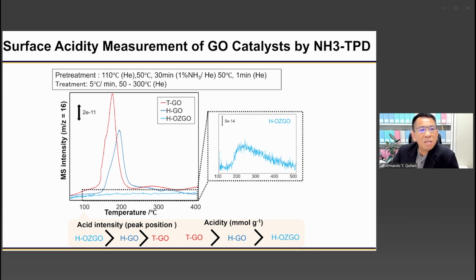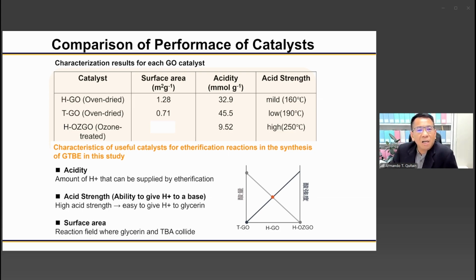We tried to analyze the surface acidity using ammonia TPD. We found out that the ozone-treated graphene oxide has the highest acid intensity peak, but talking about acidity, Tour's graphene oxide has the highest acidity. But considering a balance of acid intensity and acidity on the surface of the catalyst, we should say that graphene oxide obtained by Hummers' method performs the best among the catalysts.